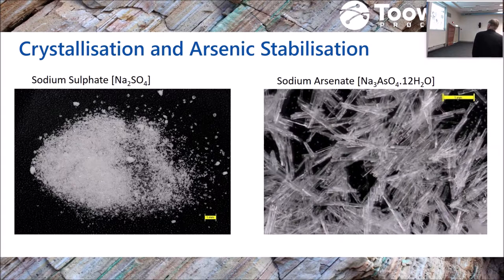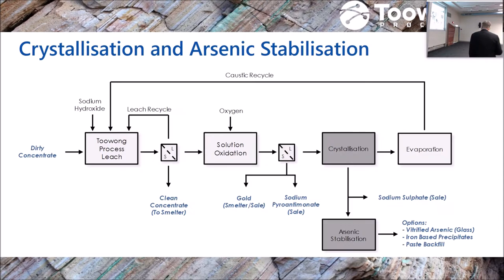So the products we make out of this are a sodium arsenate that goes to arsenic fixation, and a sodium sulfate, which is basically a detergent. The reason the historical process used a lot of sodium sulfide in here, if you're adding more sodium sulfide, that sulfur's got to come out here as a sulfate. So that's one of the bigger benefits of the Toowong process: because we don't add fresh sodium sulfide, it's only the sulfide that's liberated in the leach. For every mole of arsenic that goes into solution, maybe half a mole of sulfur goes into solution. So the sulfate we're bleeding out of the circuit here is really only coming from the arsenic that's leaching.